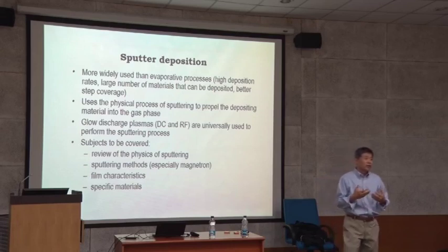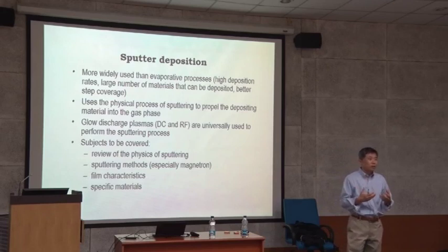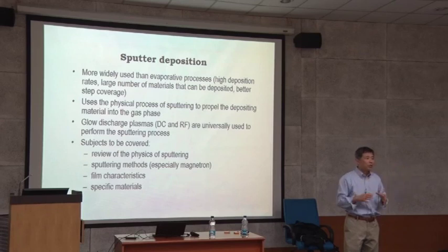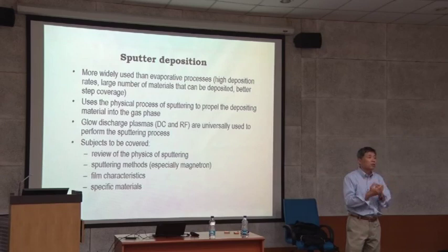That's why sputtering is so powerful: reactive sputtering. What you are all doing in oxide or nitride is reactive sputtering, not metal sputtering like a plain metal. Okay? But if you use a ceramic target, it's already reacted. So you're providing the flux from this, but you still provide an additional gas, an additional source of oxygen, to stabilize it.